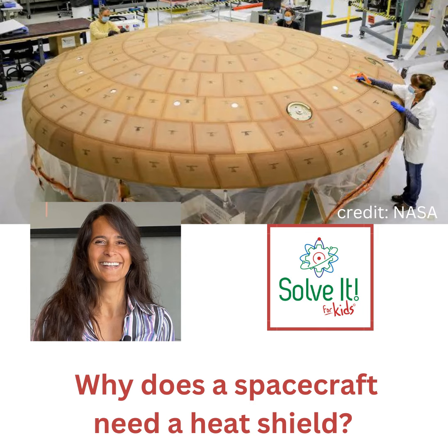And we instrumented this vehicle really well so that we have what are called thermocouples and some other sensors and devices, placed at different thicknesses through the heat shield. So we have a point of reference of what the temperature was at each of these at different points. And if a sensor doesn't give us a reading back at a certain point in the trajectory, we know that sensor got burned off. So it's been instrumented in a way so that we can really understand what margin is left on the heat shield and how it performed.